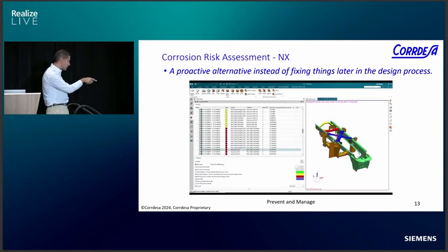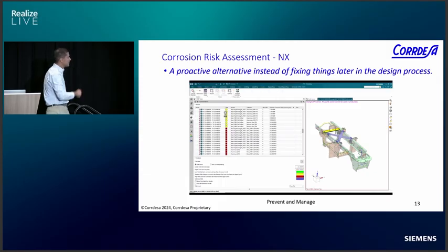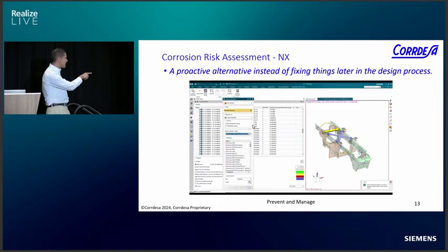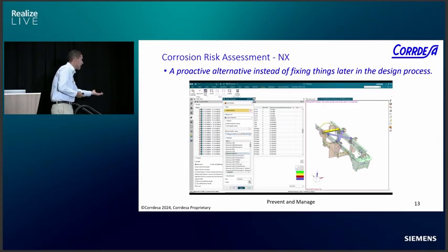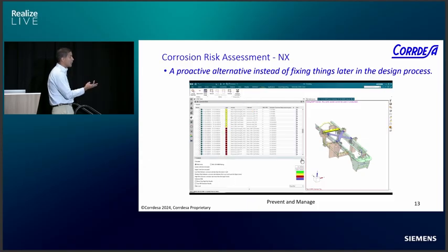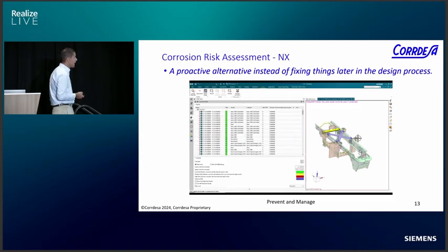Let me, for example, solve that section over here that we see that we have a corrosion rate somewhere around 230. That's aluminum 6013. And I'm changing that to aluminum 2024 because I have to be consistent. Yeah, I had aluminum at the beginning. Let me just change that aluminum for a different series. In this case, it's 2024. And what you're going to see is that now I resolve my issue. The corrosion risk was 4, now it's 2. We solved the problem.